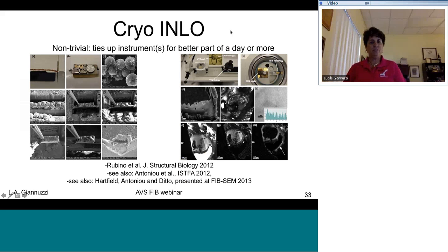Cryo in situ lift out is also possible by doing lift out with a cold chip. Again, this is non-trivial. This requires, of course, that the lift out probe chip be cold. So all this is under liquid nitrogen conditions on a liquid nitrogen stage inside of the FIB. Final thinning, and then you have to do the cryo transfer all underneath liquid nitrogen to get it into the TEM. But it is definitely possible, although it is very time consuming.